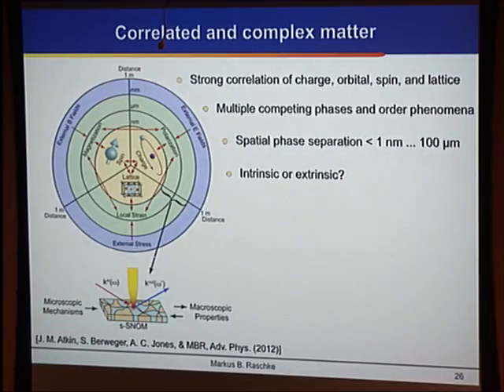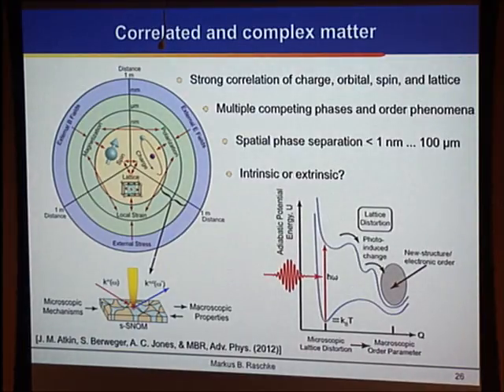And so this is where we are proposing that using local probe spectroscopy, maybe through understanding the associated domain texture with a lot of these quantum phase transitions, we can really understand the microscopic mechanism of these materials. And we do this both by looking at the material properties as we locally control temperature and cycle the materials through the interactions, or by exciting and generating new quantum states of matter through optical excitation with sufficiently high pump intensity. And the locally enhanced field in this case helps drive a photo-induced change of that quantum state, and then its evolution to a corresponding lattice distortion, through the correlation with the electronic degrees of freedom, to get a new structure or new electronic order.